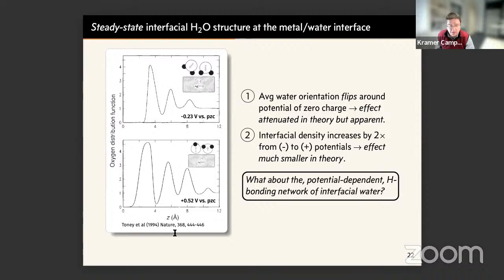There's a paper from a number of years ago, an X-ray reflectivity paper from Toney and coworkers, which inferred an oxygen distribution function that seemed to be consistent with this picture. They used a silver 111 electrode, and they measured below and above the potential of zero charge. They would argue that this data is consistent with the average water orientation flipping around the potential of zero charge.